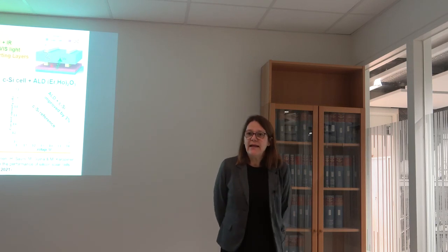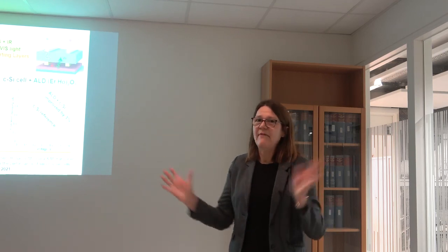I have also a question about this thermal conductivity. You nicely showed that it matters how you distribute the interface. Yes. And do you know what's the mechanism of this? And is this experimental results or is it theoretical? It's experimental, but in general for thermal conductivity, all the defects and impurities and symmetry lowerings are known to reduce the thermal conductivity, in just any material. The best thermal conductor is diamond, so it's symmetric, very light elements, and everywhere the bonds are similar and strong. So if we can get as far from diamond as possible... all those are somehow known. Of course, there are some theoreticians predicting, but they cannot predict for all the systems.